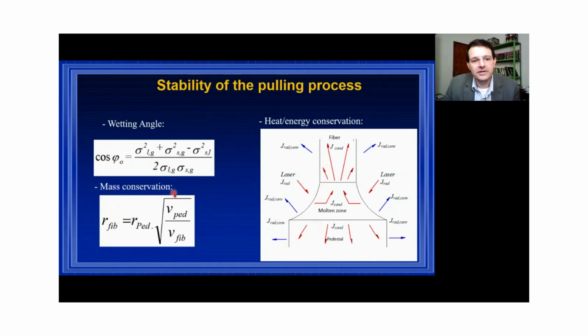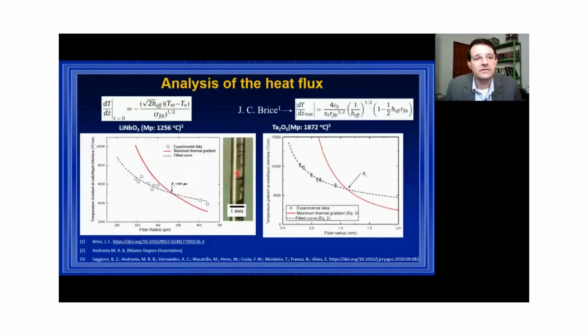By mass conservation, if you consider that all material that is melting is growing into a single crystal, you can extract the radius of the fiber as a function of the radius of the pedestal and the relationship between the pulling speeds. And through the heat energy conservation, that's the important thing, you can extract, for instance, the temperature gradients at the solid-liquid interface, where you can predict the maximum diameter of the crystal that you can produce without cracks.